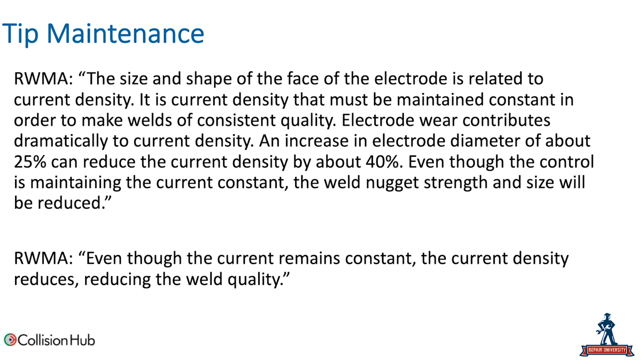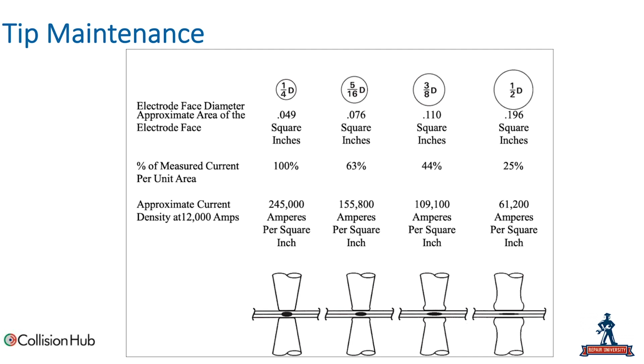The Resistance Welding Manufacturers Association goes on to say, even though the current remains constant, the current density reduces, reducing the weld quality. So as the tips of the spot welder mushroom, more power is required to make the same type of weld. And the RWMA has an illustration to show that. You can see here we've got a 1/4-inch diameter spot welding tip, very similar to what we might find in a collision repair setting. That gives us 100% of the measured current area per unit. At 12,000 amps, that current density is about 245,000 amps per square inch.